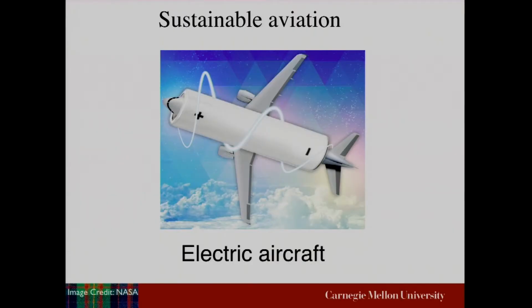And I think it's really important to frame the question in the correct way, because it's really easy to convince oneself that electric aircrafts will never be viable, but that actually is not true. You can run a back-of-the-envelope calculation. Jet fuels are 11,000 watt-hours per kilogram. We have about 20% efficiency of the jet engine. You have 2,000 watt-hours per kilogram. Best battery packs today that we have are about 200 to 300 watt-hours per kilogram. Right? This looks really challenging and daunting.